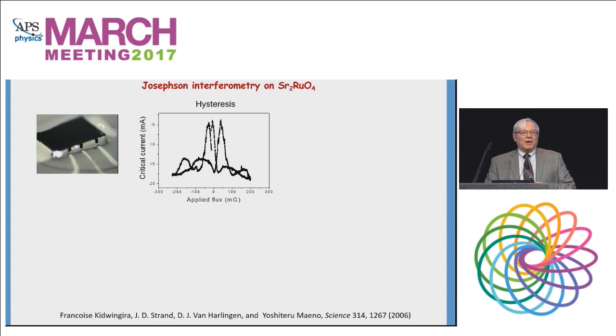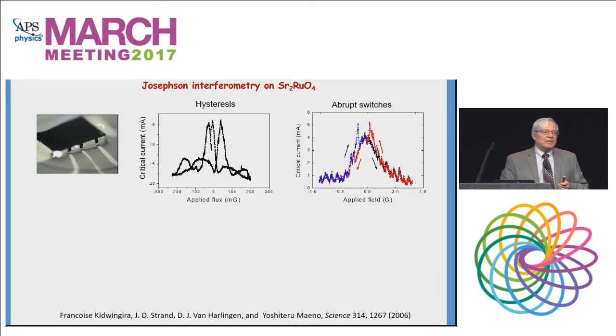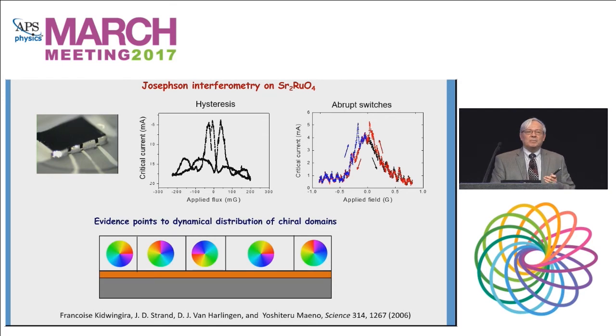The other interesting experiment we did was on strontium ruthenium oxide. This is my favorite superconductor of all time. This material is phenomenal, has really something for everyone, beautiful single crystals from Yoshiteru Maeno. In this experiment, we saw something we had never seen before. We saw hysteresis and very abrupt switches in the critical current as we measured this. And by thinking about this, we realized this could all be explained by having a chiral superconductor with chiral domains, px plus ipy, px minus ipy.